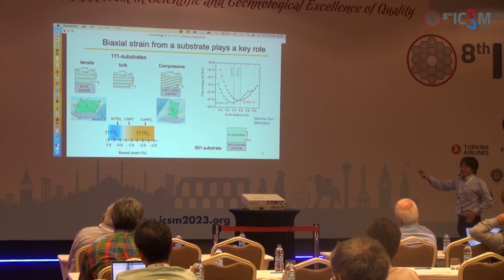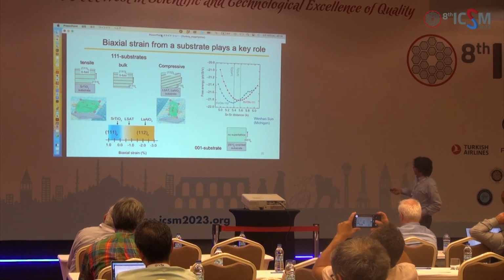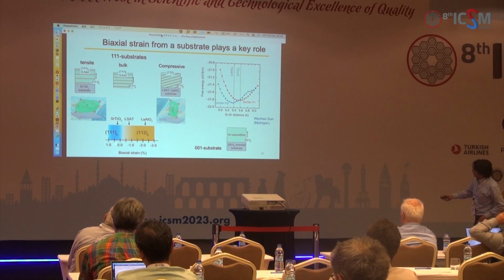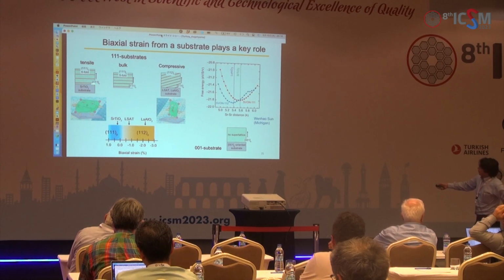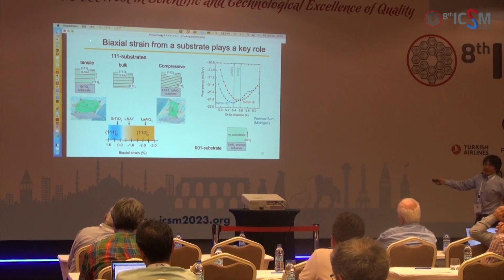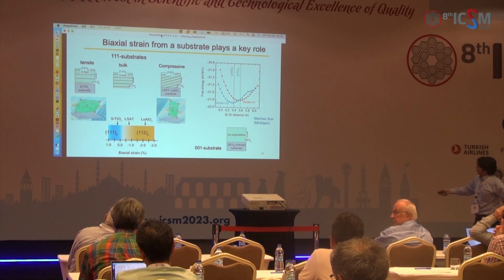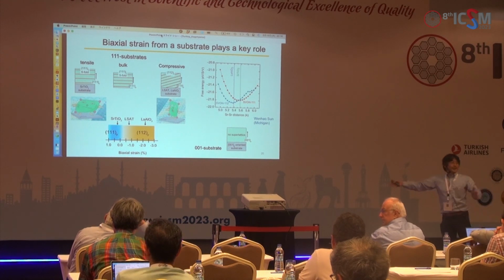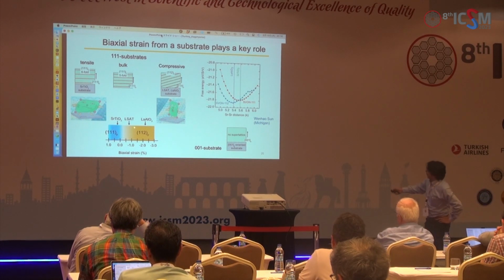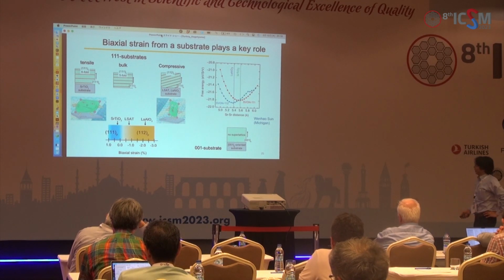Then what we have done has been summarized as follows. So this is the biaxial strain: this is no strain, but by using STO, which is nothing but tensile strain, we are able to change the periodicity along one direction. While when we apply the compressive strain, then the 112 oxygen vacancy areas are formed.